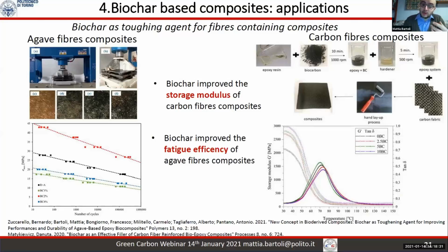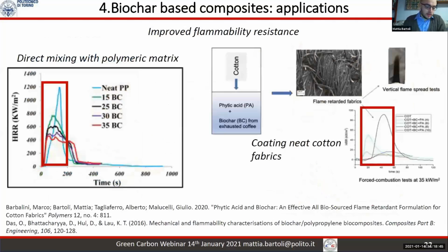And this is one of the great goals of the use of biochar for these materials, the durability. So the increased life of all the materials based on biochar is a quite strong point. As I told you before, biochar enhanced the thermal stability of the matrices and could be used to improve the flammability resistance by direct mixing with the polymeric matrix, on the left the case of polypropylene, or by simply coating, as in the case of knit fabrics on the right.